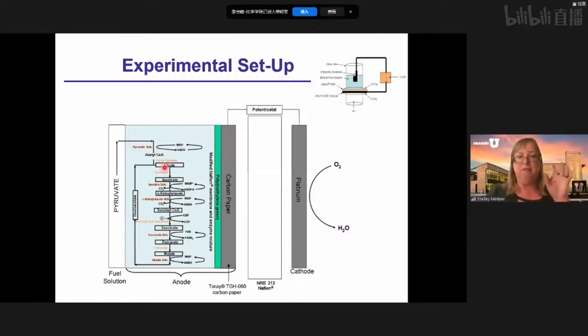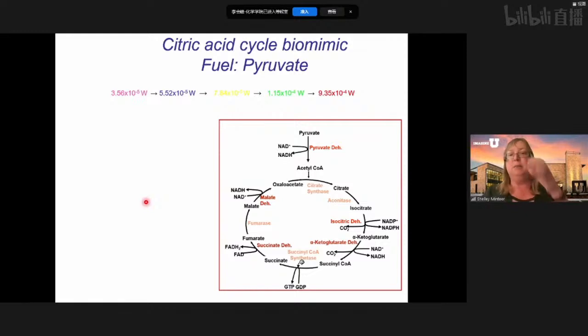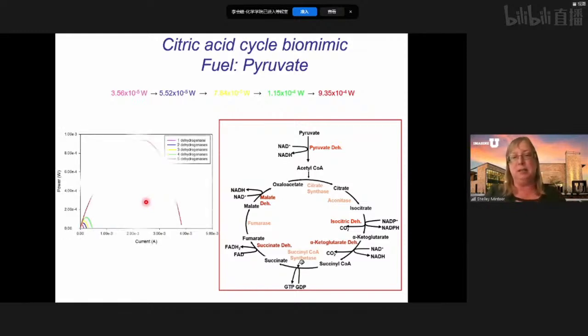So we basically made 5 different fuel cells here, or 5 different anodes at least. They all have the same separator and cathode, but 5 different anodes where we had 1 dehydrogenase, 2, 3, 4, and 5 to try to completely oxidize that pyruvate. And when we do that and we look at the power curves, it's quite interesting because we're titrating the same catalytic activity of the next enzyme down onto the electrode surface.